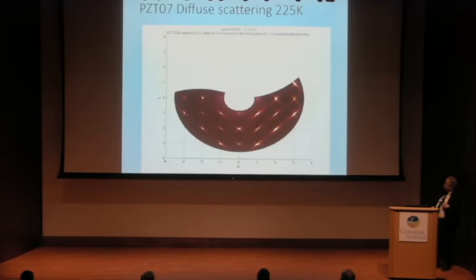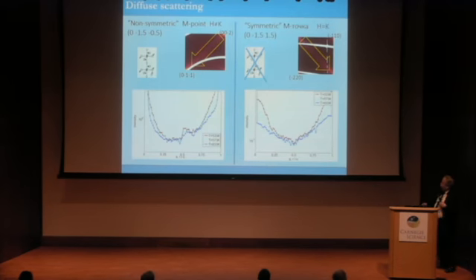That's the same, which is perfectly seen in lead zirconate titanate, PZT. In the, let me say, high symmetry 0, -1.5, 1.5 peak, we have nothing, and here there is no contribution from the oxygen octahedral tilt. But if we do have a contribution from the oxygen octahedral tilt, we do have some intensity, but that goes up not at the endpoint, but aside of it.